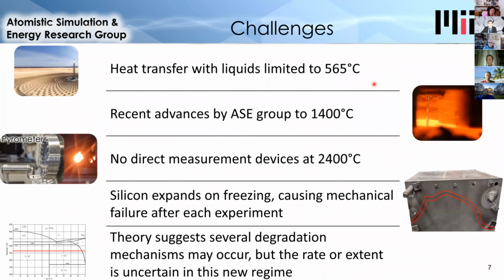And so before I get into how we actually tried to make this happen, I just want to expand on some of the challenges with running these experiments. So like I mentioned, commercially, heat transfer with liquids has been limited to around 565 degrees Celsius. In the last few years, our group has exceeded that and reached up to 1400 degrees Celsius where we're pumping molten tin. And now we're trying to go up to 2400, which adds some new challenges.